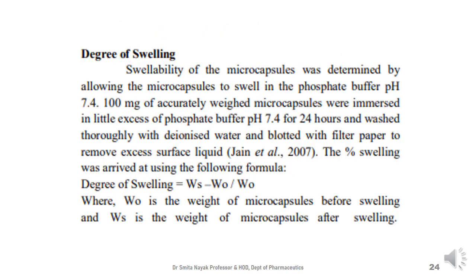Some polymers used in microencapsulation have the property of swelling. In such cases, it is necessary to study the degree of swelling once the microcapsule is wetted. Microcapsules are placed in phosphate buffer pH 7.4, weighed initially, and weighed again after 24 hours. The degree of swelling is determined as (Ws − W0) / W0, where Ws is the weight of the microcapsule after swelling and W0 is the initial weight.